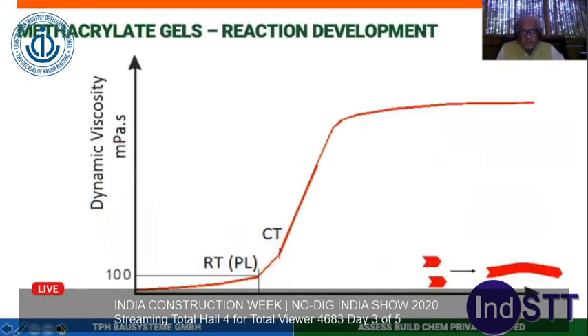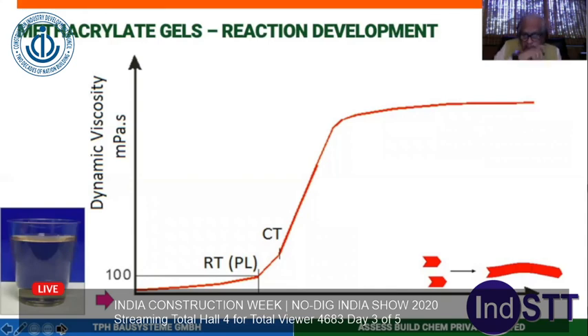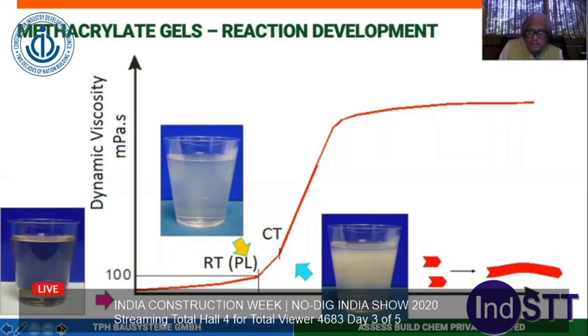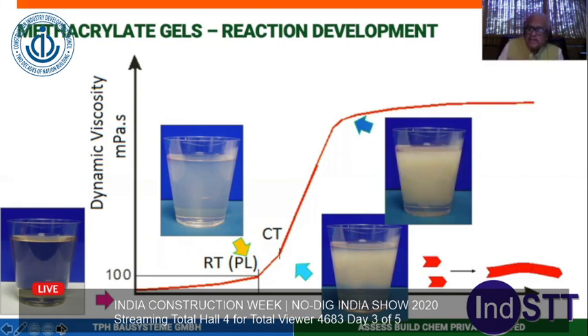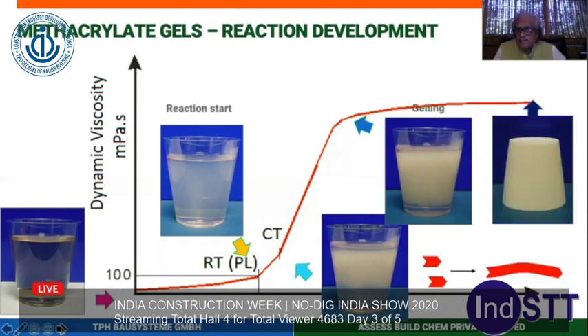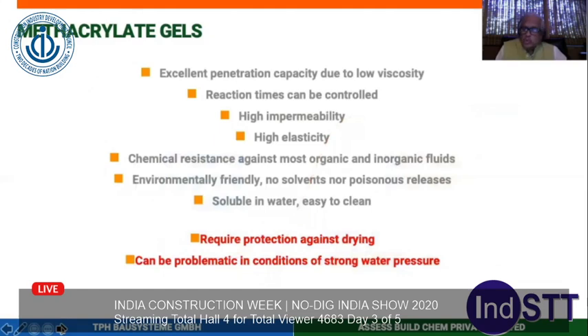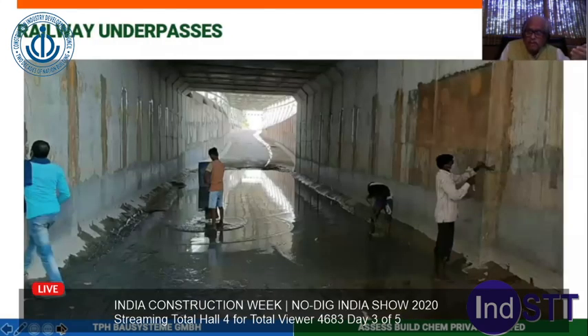So they react very fast. You can see, when it reaches say a viscosity of 100 mPa.s, it is still pumpable. Then the reaction time, in about 10 to 12 seconds, you can control it. Then it starts increasing in the gelation time, and it is gelled. Within about 20 minutes, it is a proper gel. I will show you one or two videos to show you the type of gels. These gels are normal, and they can also be fortified with acrylics to give them characteristics so flexible that you can convert them into a joint filling material.